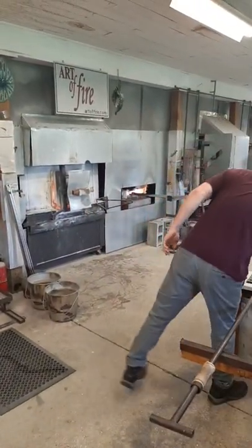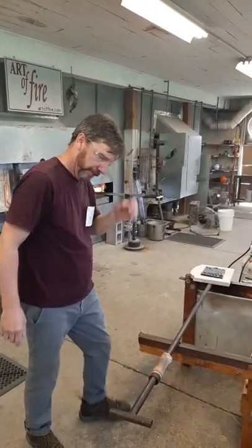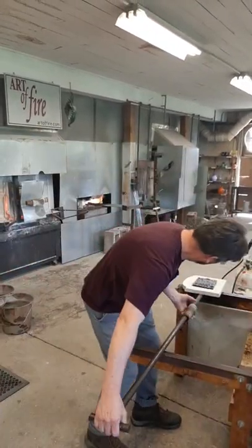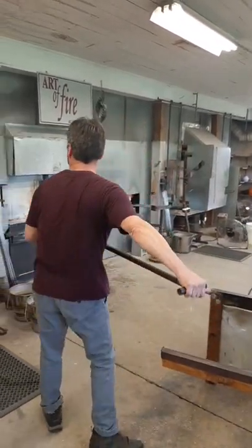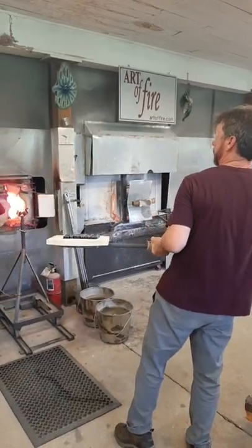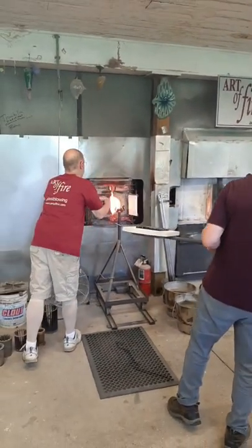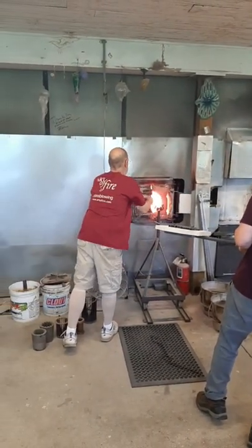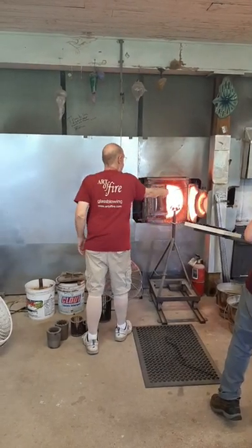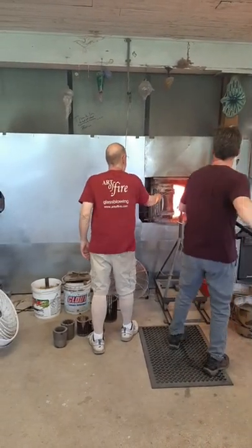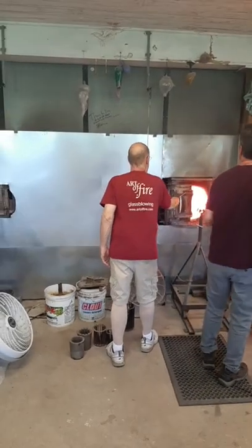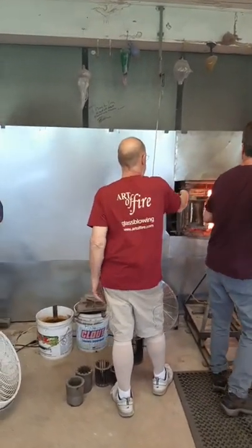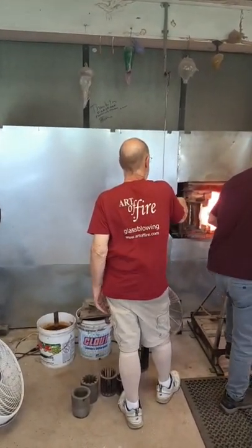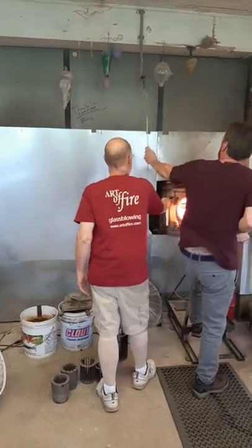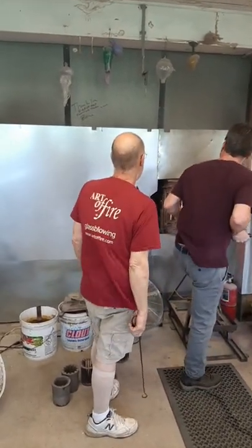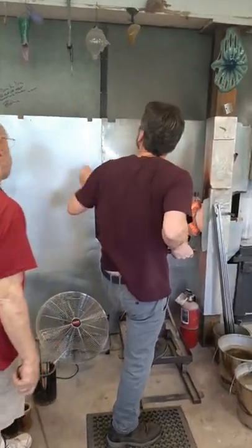Okay. Well, you know what? He's going to need the gloves still because he's going to be moving this pipe around and he's going to be squeezing the murrini a little bit. So those murrini came out of our annealer at approximately 900 degrees Fahrenheit. That's what the annealer runs at. And so what he'll do now is that preheats them so they don't crack when he enters the furnace, the glory hole, at about 2300 degrees. And he'll go gently into that and start warming them.